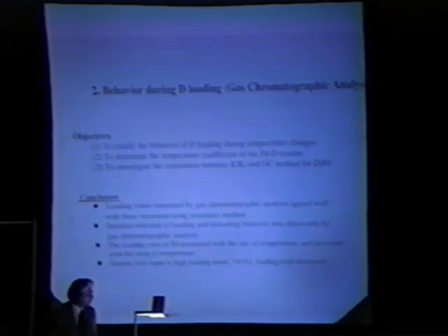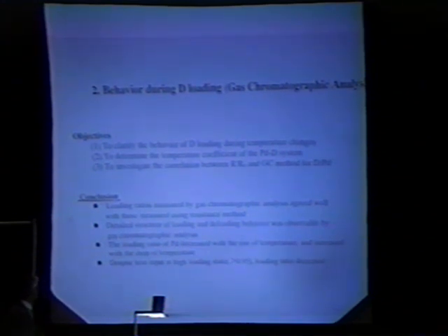The conclusion of this experiment: the loading ratio measured by gas chromatographic analysis agrees well with that measured using the resistance method. The detailed structure of loading and deloading behavior was observable by gas chromatographic analysis. The loading ratio of Palladium decreased with the rise of temperature and increased with the drop of temperature. Despite heat input at the high loading stage, the loading ratio decreased.